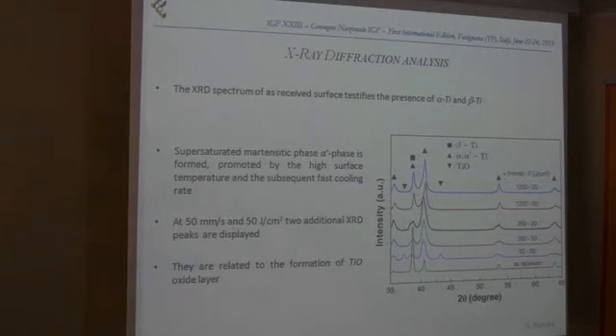In order to support this information, we also performed X-ray diffraction analysis, and basically what we could see was that the increase of the hardness could be attributed to the formation of alpha prime phase, which is a supersaturated martensitic phase, harder than the baseline material. And we also verified a different peak for the test that I showed you before, so the lowest scanning speed and the highest pulse fluence, which confirms the formation of the oxide.